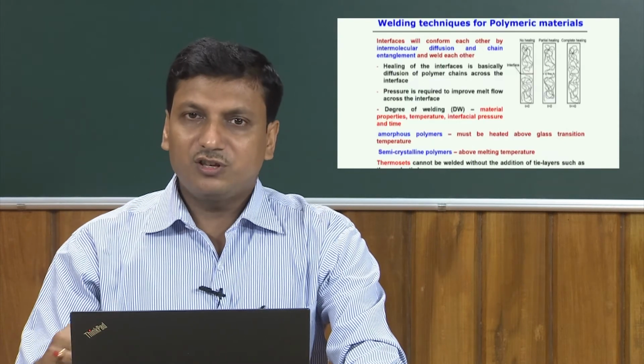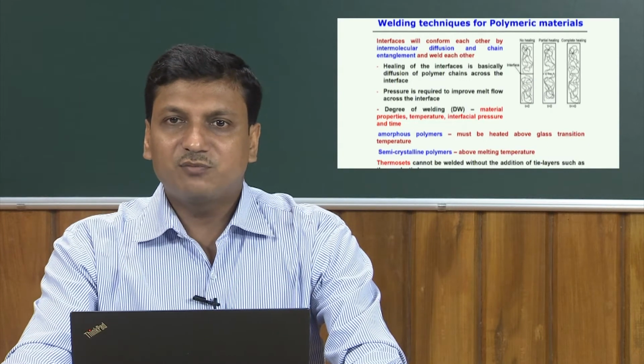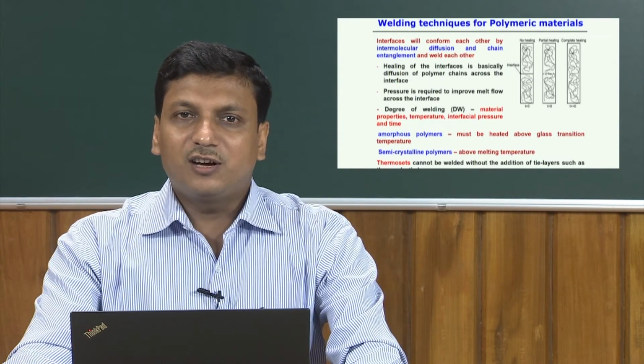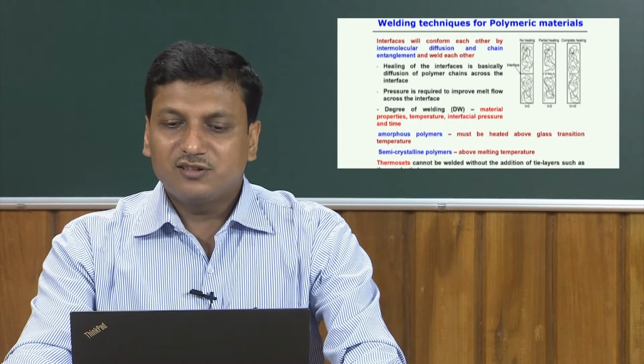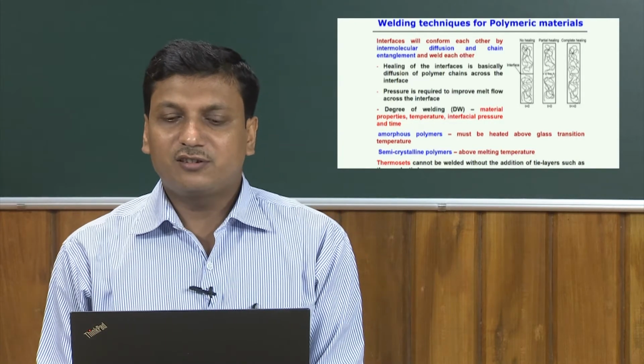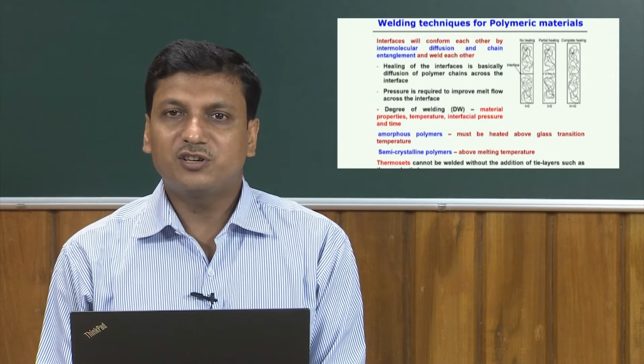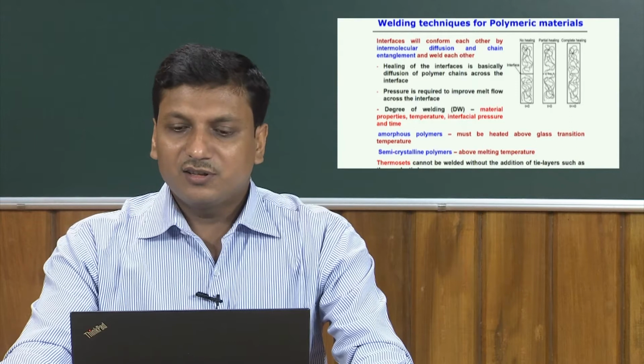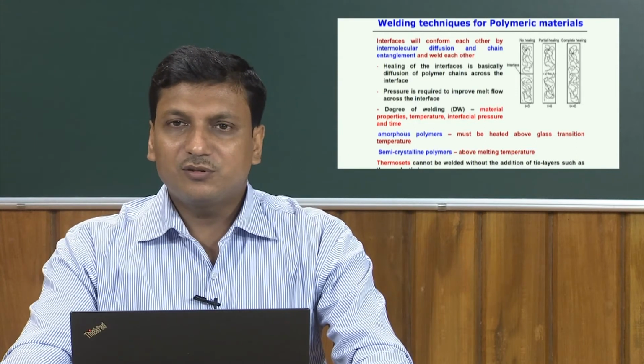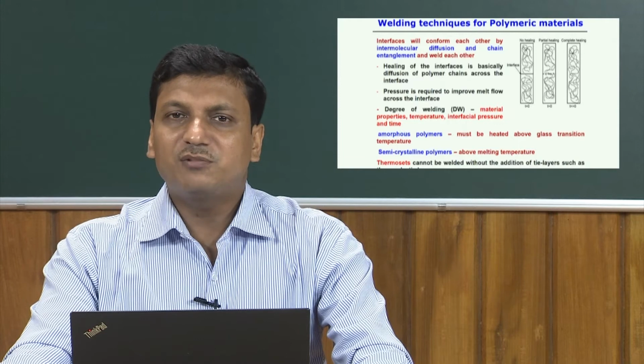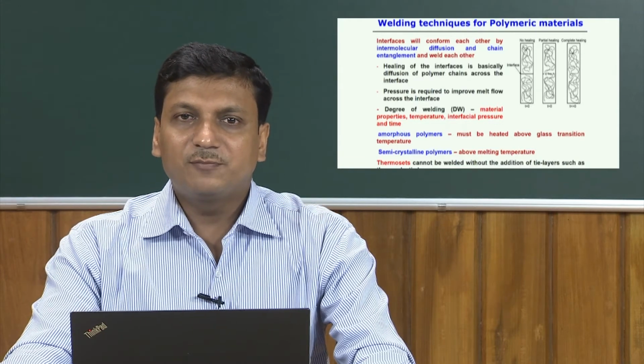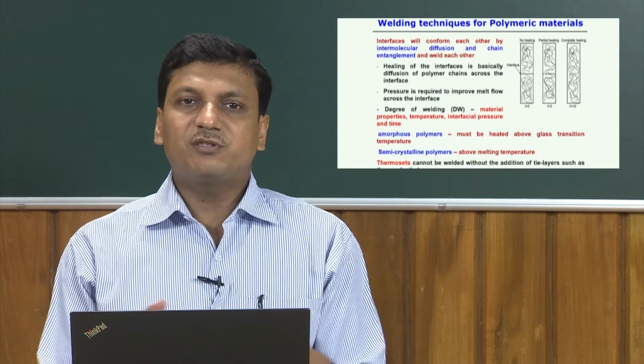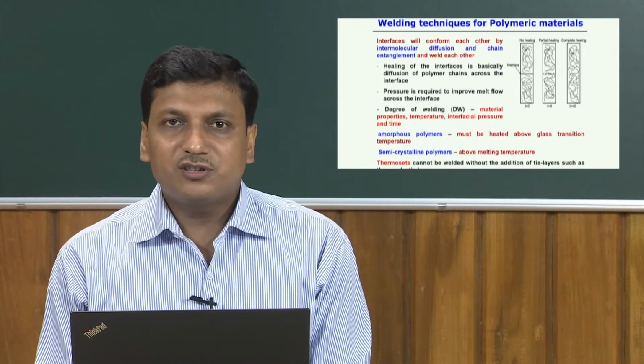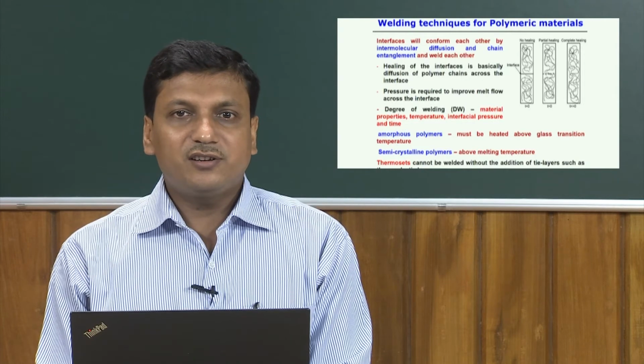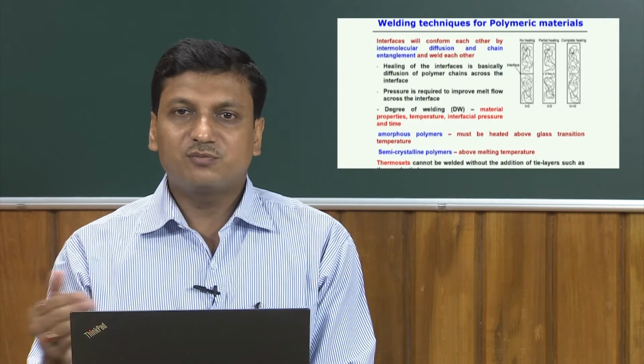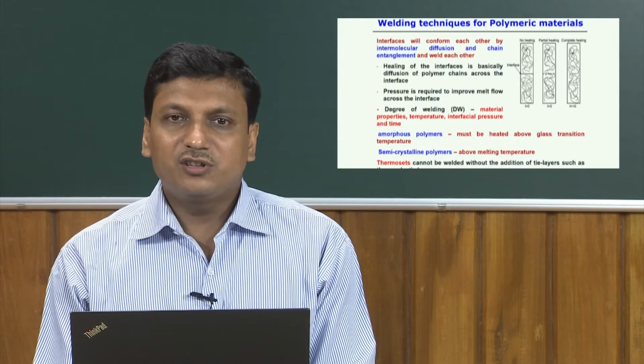If you look into more detail at the welding techniques for polymeric materials, in principle, from the figure on the right-hand side, when the two interfaces come in contact there is no heating. Then with the application of heating there is partial heating at time t greater than 0, and finally we reach complete heating after sufficient time. In principle the interfaces conform with respect to each other such that intermolecular diffusion and chain entanglement occur, and that is responsible for forming the weld or joint between the two polymeric materials.